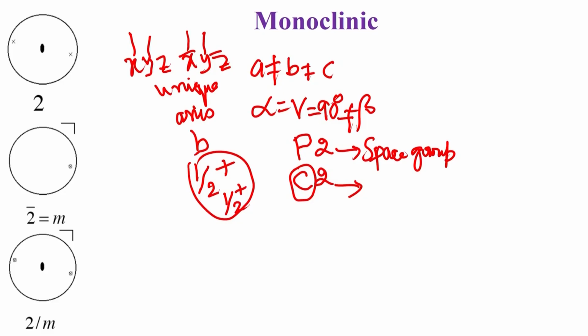The next system which we will take up is the point group symmetry corresponding to the mirror plane. In this particular case, as you will see here, there are different kinds of notations. If we write the mirror symmetry like that, it means that the mirror is in the stereographic projection equatorial plane, which means the mirror is in the plane of our presentation, and you see here that the x, y, z and the generated mirror component, which is x, y bar, z, are on top of each other.